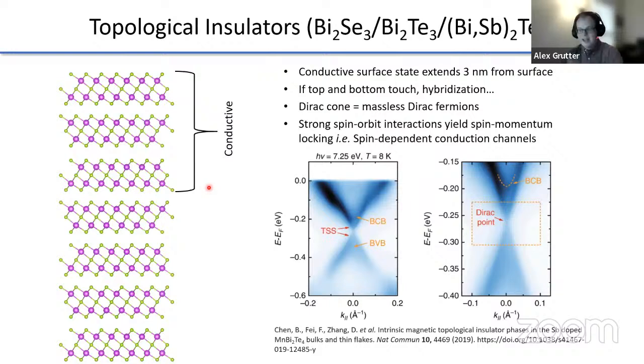Now, these surface states appear at both the top and bottom of the material. And this, of course, means that if you have a topological insulator below 6 nanometers thick, then you start to get some weird hybridization effects between the top and the bottom. And in fact, the hybridization can destroy the topological surface states.